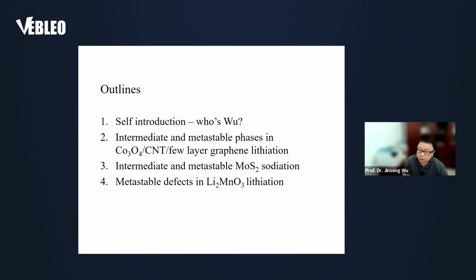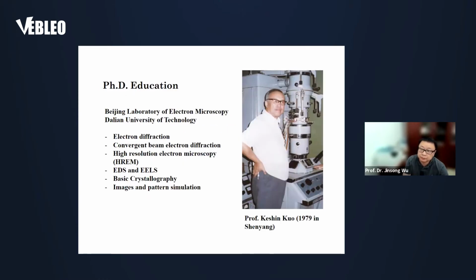And then I will talk about the intermediate and metastable phases during the sodiation of MoS2, the molybdenum disulfide, and then the metastable defects in the amorphization.